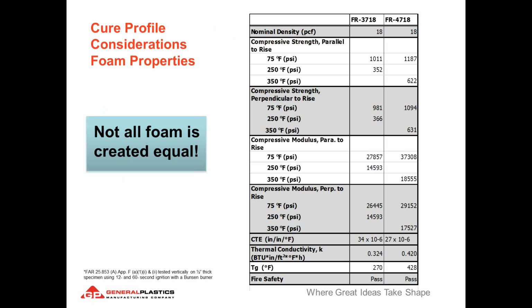So cure profile considerations. So of course, foam is much more insulative than metallics. Here I've picked 2 of our 18-pound per cubic foot materials. And just in general, we look at the room temperature data for compressive strength and modulus. They're really quite similar. Now, as you increase temperature, the 3718 starts to soften and weaken as it approaches its glass transition temperature at 250 F. Whereas the 4718, with a much higher glass transition temperature, is still quite a bit stronger, even to 350 F.